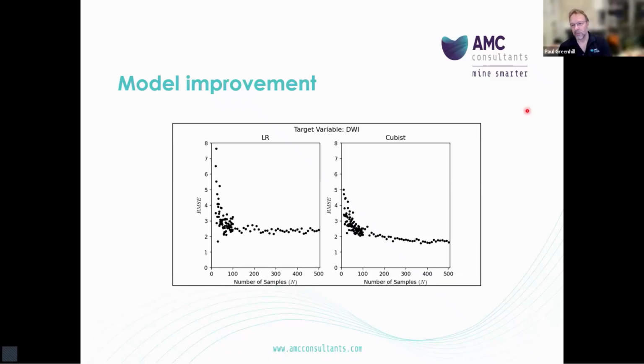So we can use this sort of information to determine a threshold at which either the error of the predictive model is sufficiently low as to be fit for purpose, and that's an important concept, or further testing will not significantly improve the predictions. So when I talk about fit for purpose, the objective here is to reduce the risk associated with this type of prediction approach, or prediction of the metallurgical properties. And that risk is obviously associated with the stage of the study.